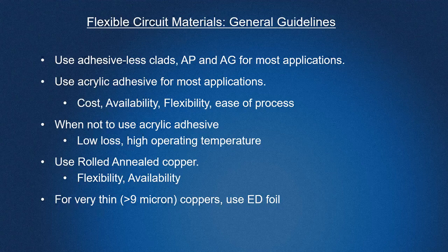Where you can run into trouble is when the material is mechanically stressed during the high temperature point where it's soft. So if the material is flexed or bent when it's, let's just say, 150 or 200 degrees Celsius, it won't be decomposing, but it will be very, very soft and very vulnerable. Now, when it cools down, it goes back to normal and no harm's done. But if you have any separation or any other issues while it's at the higher temperature, you've got a problem. So those are some of the limitations with the acrylic.